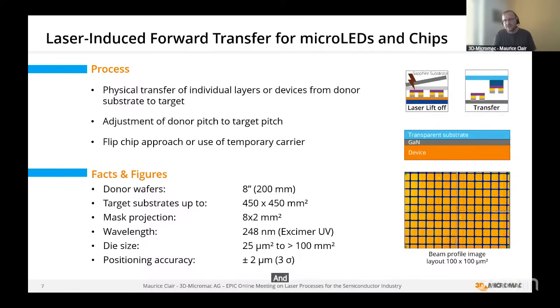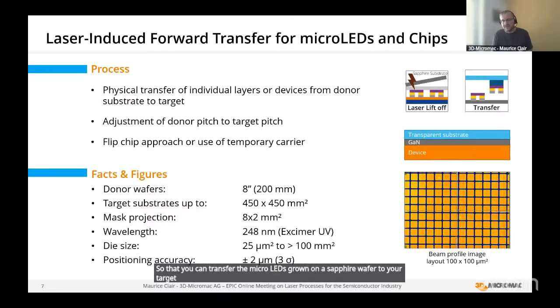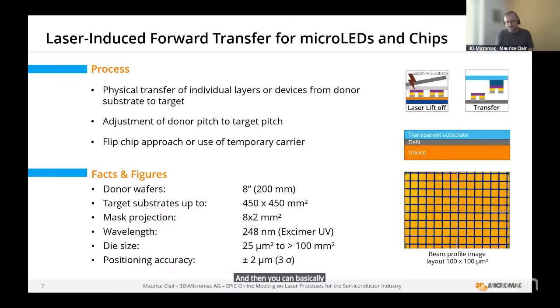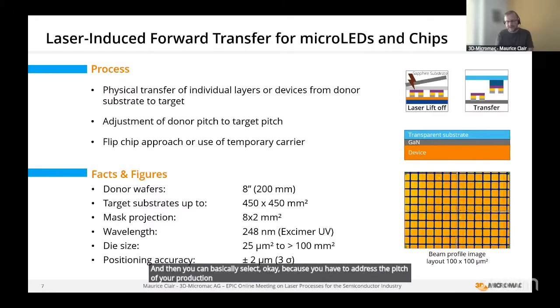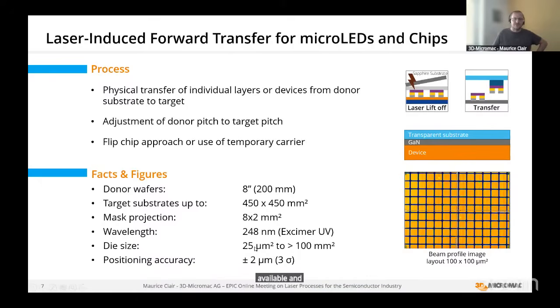And the basic idea what this was developed for was micro LEDs, so that you can transfer the micro LEDs grown on a sapphire wafer to your target substrates, which typically are glass panels in the range of 450 times 450 square millimeters. Because you have to address the pitch of your production to the pitch of your device, you can select: do you want just one of those areas transferred, or do you want everything transferred? There are all kinds of designs available. And the smallest die sizes that we've transferred are 25 micron, so around about 5 by 5 micron.